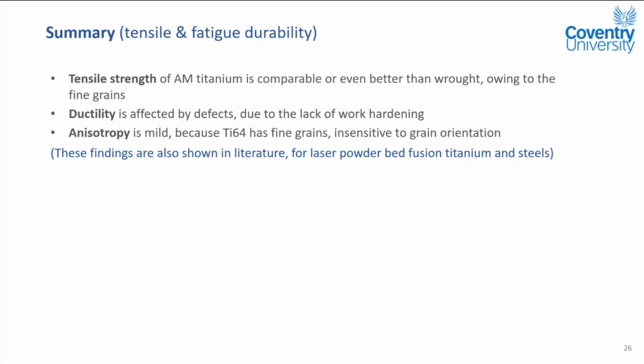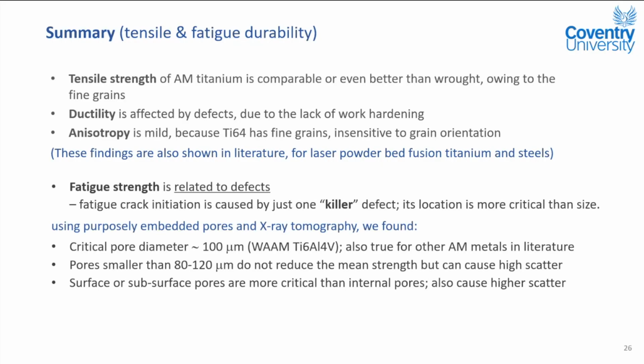So with that, I'd like to conclude that the tensile strength is very comparable or even better than traditional wrought because of the fine grains in additive manufacturing. Ductility is affected by defects and due to lack of work hardening in titanium. Anisotropy is mild because titanium alloy has fine grains. These findings I wrote in blue agree with independent research in the literature. In terms of fatigue, it's all related to defects, all related to one killer defect, and its location is much more critical than its size.